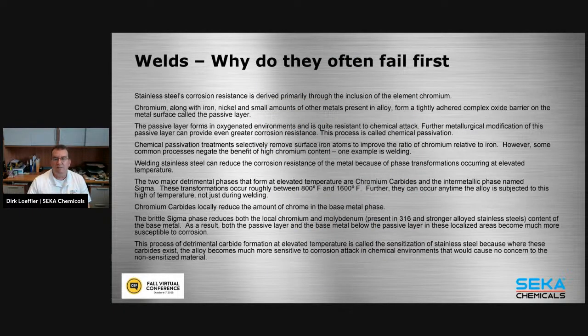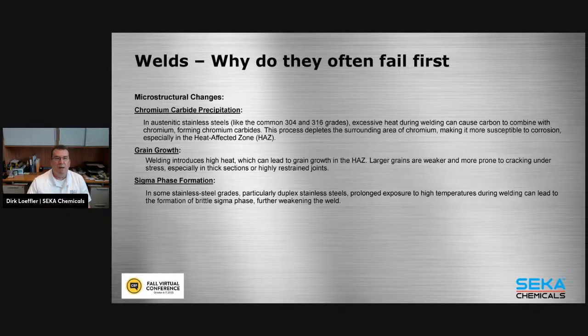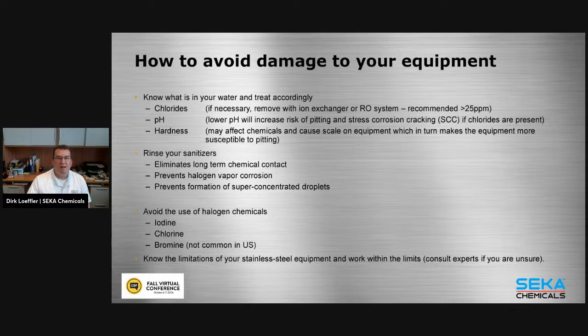We talk about why welds fail first. The intergranular corrosion: the heat creates again the chromium carbide, and that will cause a very weak layer, and we call it a sensitizing layer. It is no longer able to produce a passive layer like the rest of the stainless steel, and then the passive layer breaks down and causes problems. Again, we have first chromium carbide precipitation in what we call the heat affected zone. The grain grows, and we also have what's called a sigma phase formation. You guys can go through this. I'm kind of flying through this because I'm almost out of time.